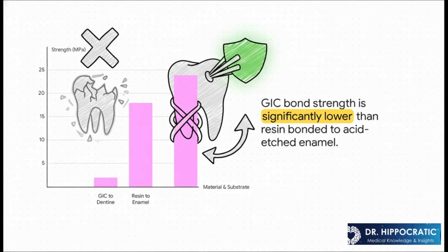And wow, this chart just lays it all out, doesn't it? When you put GICs side by side with modern resins, which can get up to 16, even 20 megapascals, you really see that huge gap. This is exactly why understanding this cohesive weakness is so critical for a dentist. It tells them that GICs are great for low-stress areas, but probably not the best choice for rebuilding a major chewing surface that takes a real beating.